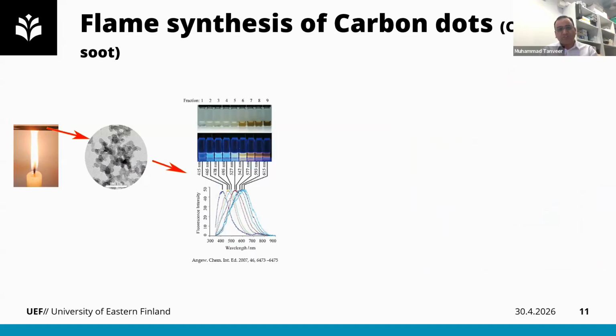As far as the earlier studies are concerned, carbon dots were produced through soot derived from candles. In these strategies, the soot is treated with acid oxidation systems, and the different particle ranges are then segregated. After that, their surface functional properties are also tuned up. This enables the material to tune its photoluminescence features in different regions of the UV-visible spectrum. As you can see in this diagram, different sizes of the carbon dots have been segregated and then they are used in different regions. So there is a lot of scope here to use candle soot.